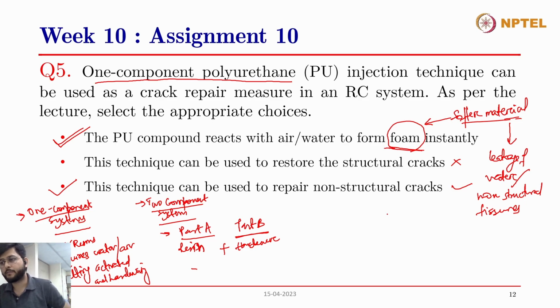When it gets set, it becomes very hard, and it allows for a good bonding between the two regions across the cracks. So whenever after the injection of the PU, when epoxy is injected, since epoxy is a harder material than PU, it will puncture these foams, the foam that is formed within the cracks, and it will fill those regions, so that first of all the water leakage is stopped by injection of the PU foam, and once the leakage has stopped, then only we'll be able to inject the epoxy, because epoxy